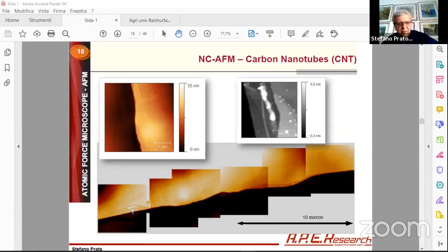I don't know if you can see very nicely, but the carbon nanotube is very, very long. You see, all this. Can you follow my mouse? It is going and finishing here. So this carbon nanotube is, as I showed you before, between 2 and 3 nanometers in height, but is very, very long. It is 40 microns long. So the ratio between length and height is more than 1000.